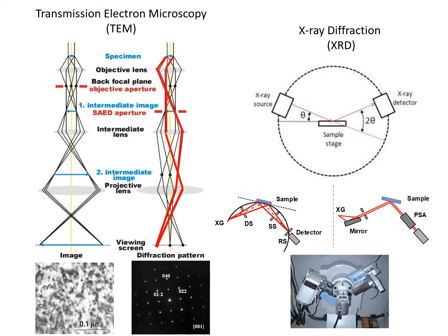And what happens then is that these electrons, when they're detected at a certain point, the ones that have been scattered at a certain angle, you can see certain points of high intensity. So there is more chance that more electrons get scattered off at particular angles and can be focused to a point on a diffraction pattern. And that reflects this phenomenon where we get constructive interference for those waves that are scattered in certain directions.